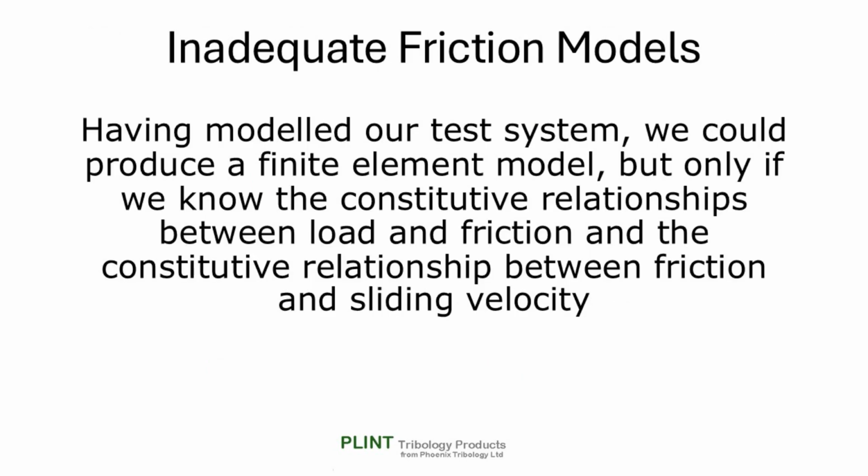Having defined our model test systems with the necessary mechanical information regarding mass, stiffness, inertia, etc., we could in theory produce a finite element model of our test system. We have, however, managed to avoid one key requirement: the thorny subject of the constitutive relationship between load and friction, and the constitutive relationship between friction and sliding velocity.